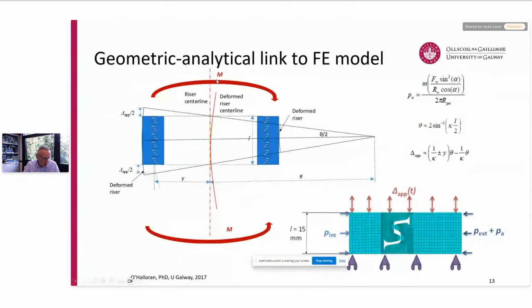This slide shows basically the geometrical analytical link to the finite element model. This is essentially a geometrical model, which is a little bit complicated, but if you look on the left-hand side, you can see a longitudinal section through a flexible riser, and you can see the multiple riser nub groove contacts in the pressure armor layer. What we're saying is this model allows us to convert bending moment, which we get from the global dynamic model, into delta applied. So we can estimate the relative displacement from essentially the curvature and the angle of rotation theta of a typical section of this riser. We can estimate the delta applied, and the equations are on the right-hand side there.